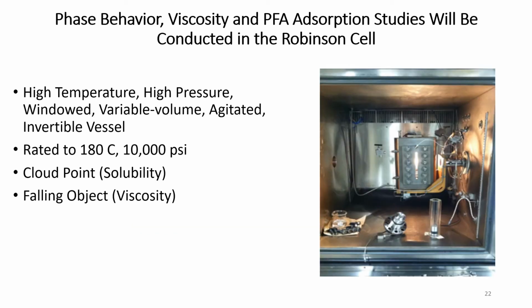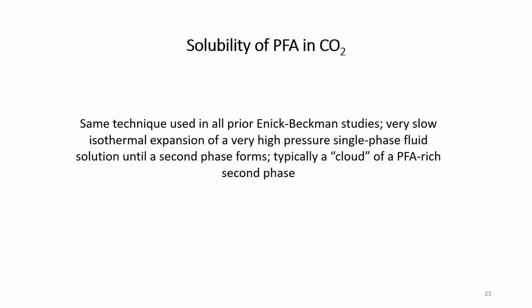In our lab, we have a high temperature, high pressure, windowed variable volume, agitated invertible vessel that goes up to 180 degrees Celsius and 10,000 psi. We call it the Robinson cell. With it, we will take solubility and viscosity data, all while being able to see what is happening inside the cell. The solubility experiment is simple.